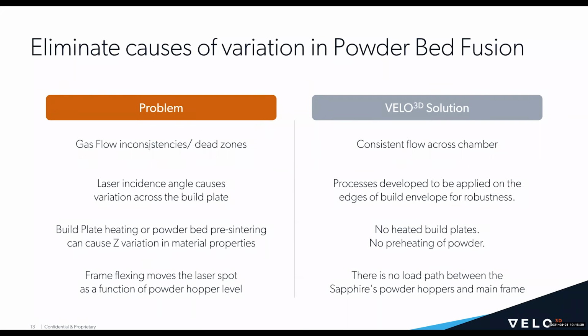First off, in the X and Y direction, we have gas flow inconsistencies. Dead zones are a common problem. We have consistent gas flow across our chamber, and we don't have any obstructions like recoaters in the way. Additionally, laser incidence angle can cause variation across the build plate. For the VELO3D processes, they're qualified and developed not only directly underneath the laser, but also at the extremities of the build plate, so that day in, day out, you don't see that variation with respect to location.